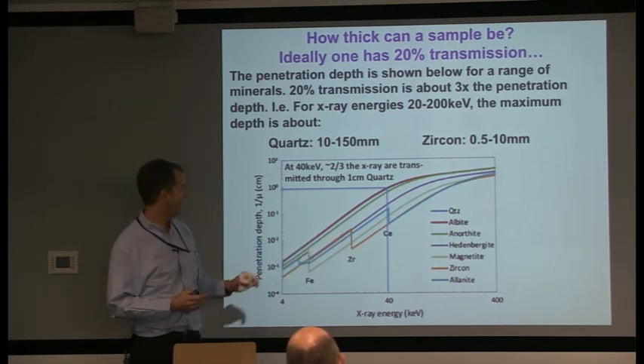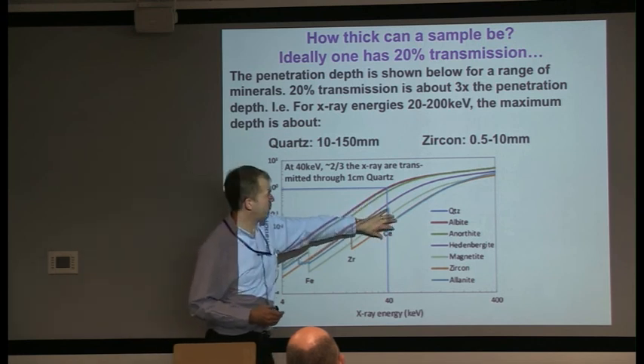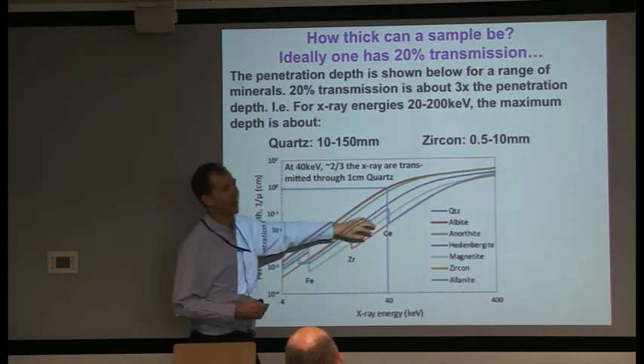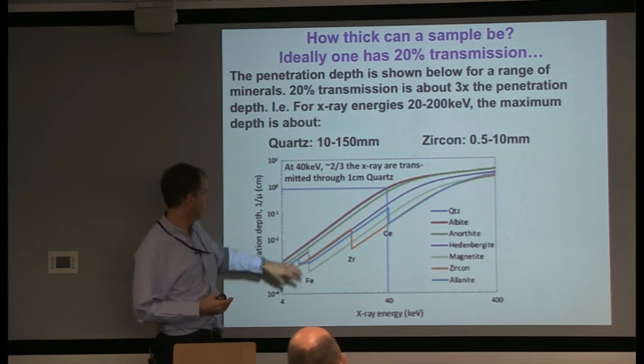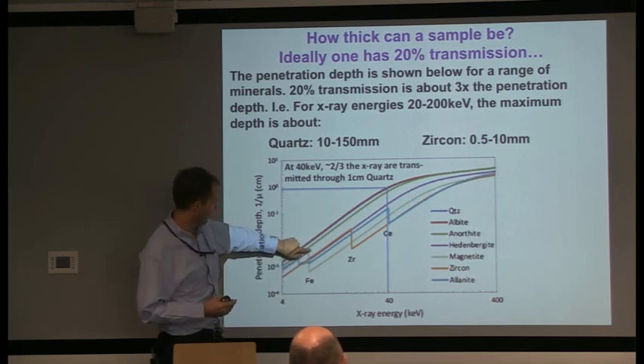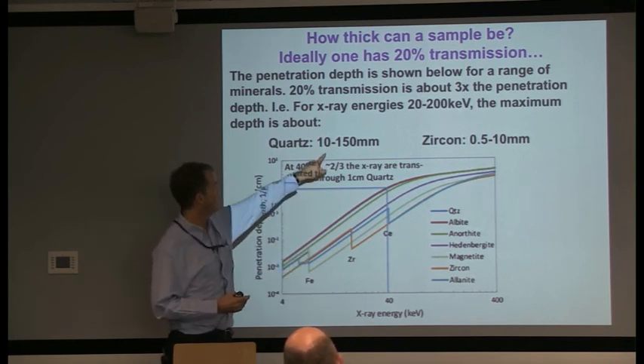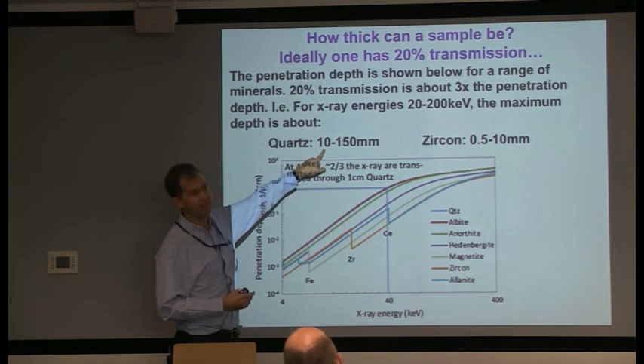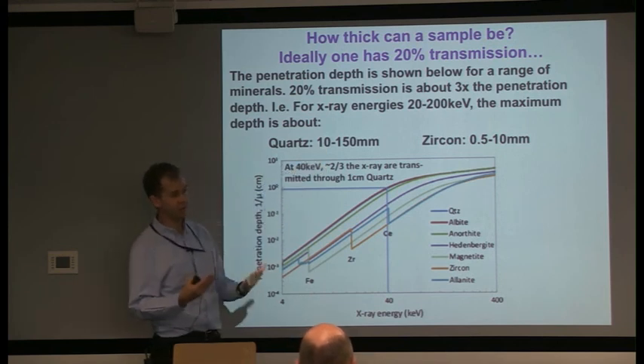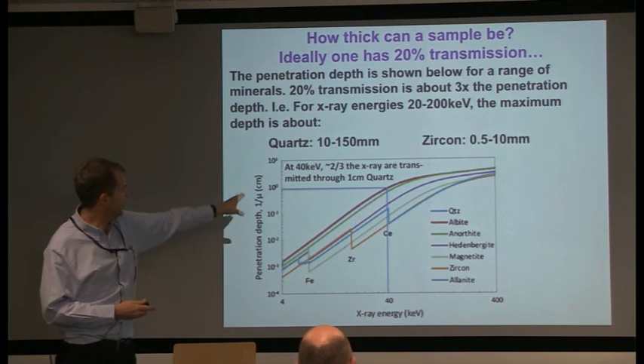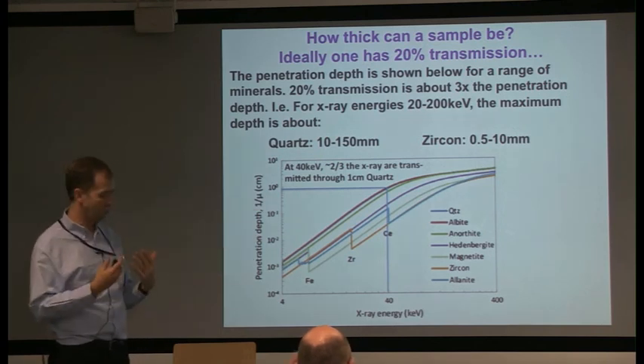That's great if the edge is in the range where you get penetration. In most cases the edge is lower, so if we're down at 10 keV, I'm only going through a couple of millimeters max of soil, which isn't enough for statistics. So you need to really think about what you're doing and plan your experiment.